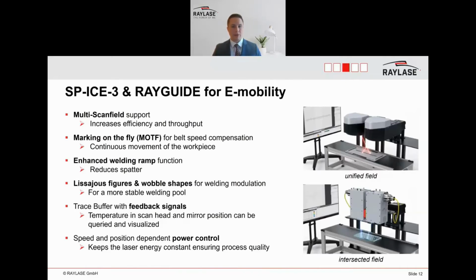So if you, for example, have a corner and you have to decelerate your scanner, or your mirrors, the effect would be, without this speed and position dependent power control, that you have a burn-in or something because the laser power is constant. If you can correct that, you can keep the laser energy constant during the process to ensure the process quality.